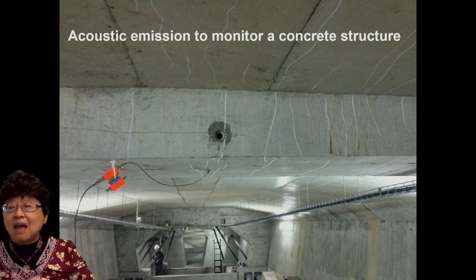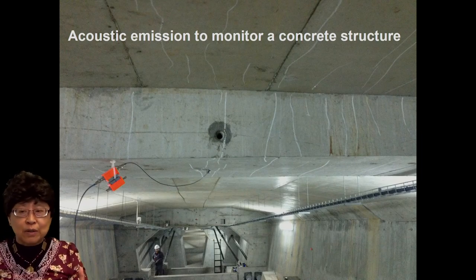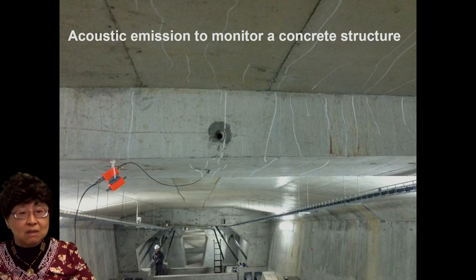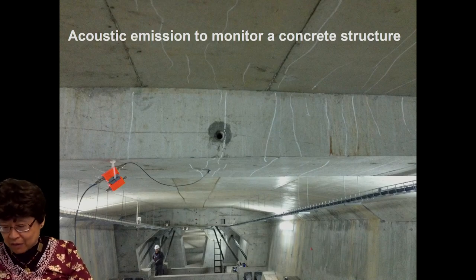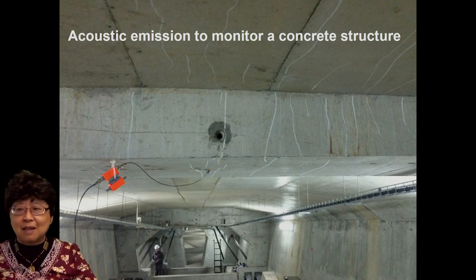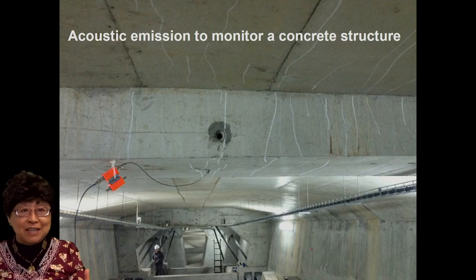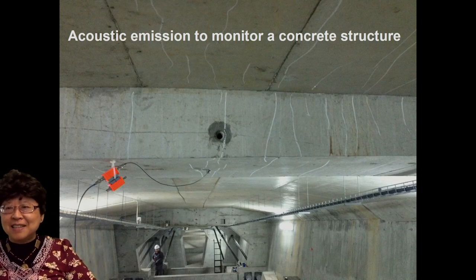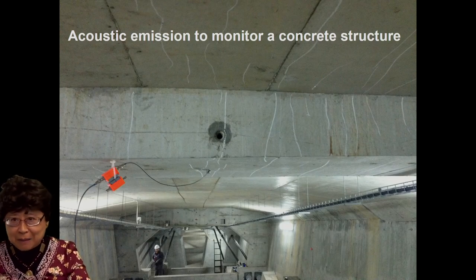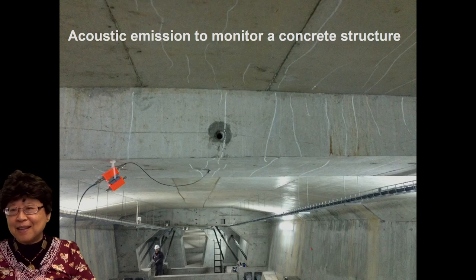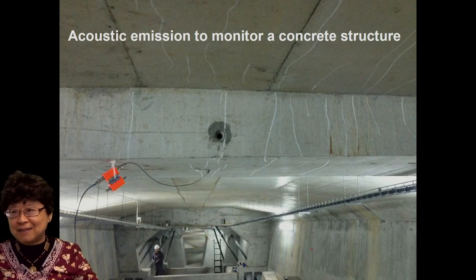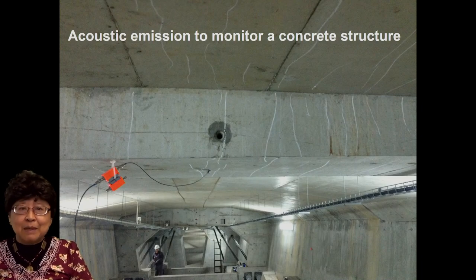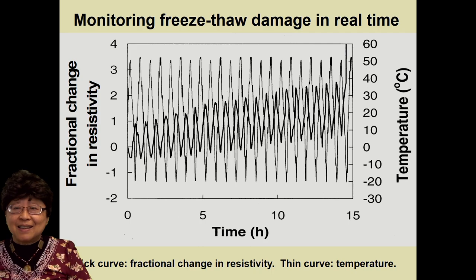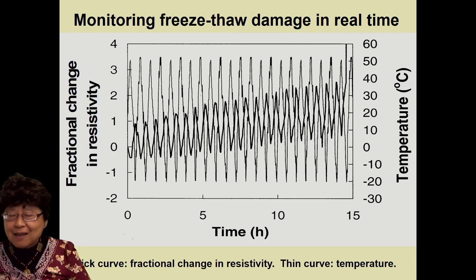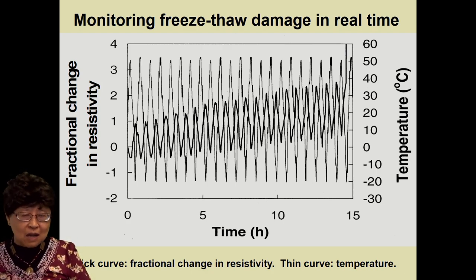But anyway, it's sound, and when damage occurs, just like breaking things, sound comes out, and so by listening, one can monitor. But after it's formed the crack, it's finished giving the sound. So you have to listen to the thing all the time. Otherwise, you'll miss something. And also you can listen here and there, but not everywhere. So it's a limitation. But what I have is not use any sensor, but use electrical resistance measurement to monitor the freeze-thaw damage in real time.